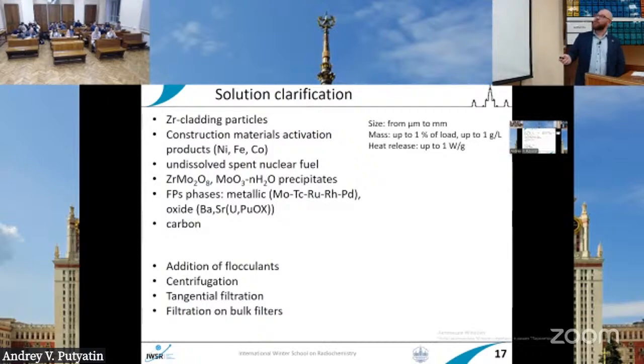There is a formation of the precipitates of zirconium with molybdenum that I mentioned several times. It is one of the main problems during the reprocessing of spent nuclear fuel, at least in the head operations. So we need to remove it.